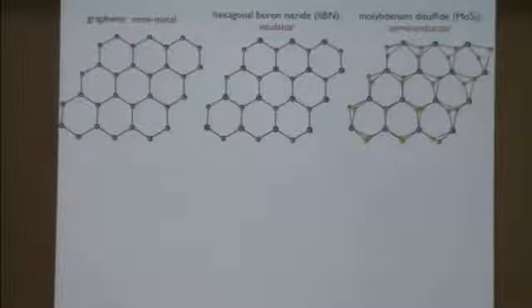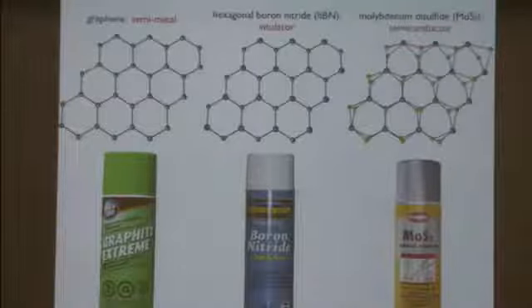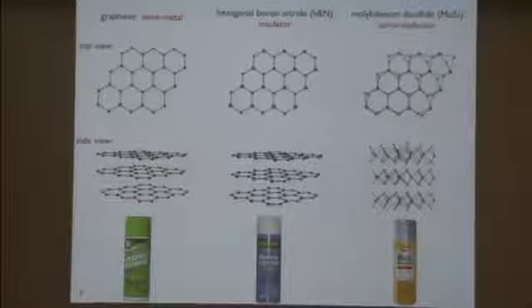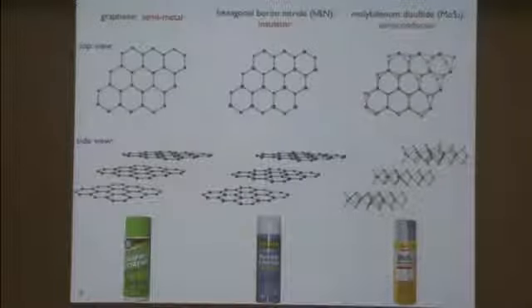And what unifies all of these materials together is that they can all be purchased in aerosol cans. And the reason for that is that they all make excellent dry lubricants. And they make excellent dry lubricants because all of these materials have intrinsically layered structures. So they're formed out of stacks of two-dimensional crystals, which have very strong chemical bonds within the plane, but have very weak coupling between planes, so that the layers can slide past each other without breaking, which provides lubrication. And that same sliding for lubrication is what allows us to peel the layers apart and isolate individual atomic layers for study and making devices to look at the physics of these materials.